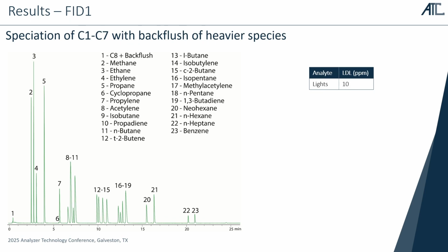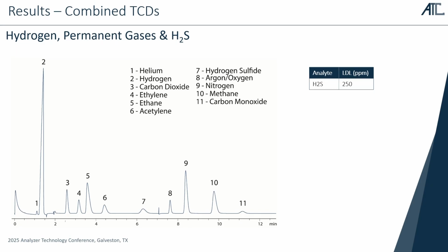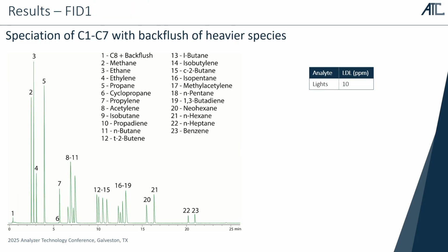We don't know if it's 50 ppm of C8. We don't know if it's 50 ppm of C9. This is all going to be resolved on our second FID using our second microconvection oven. As you can see from this chromatogram compared to the one before it, the peak shape is a lot cleaner and a lot smoother. This is on a capillary column using our temperature-controlled microconvection oven.